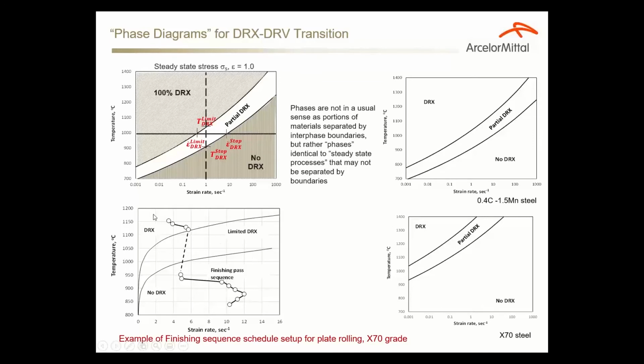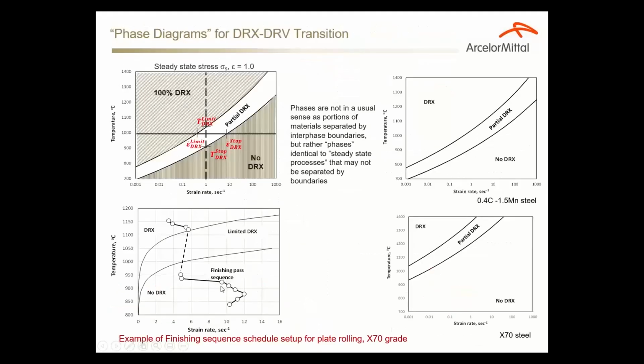We build this kind of diagrams for different kinds of steels and actually use this as an example of how we set up the plate rolling finishing schedule to produce no dynamically recrystallized steel. See, we designed the first 4 finishing passes so as to provide as much dynamic recrystallization as possible. But then the temperature went down, so we proposed to have the bar on hold and drop the temperature substantially and finalize the dimension in the no dynamic recrystallization range.